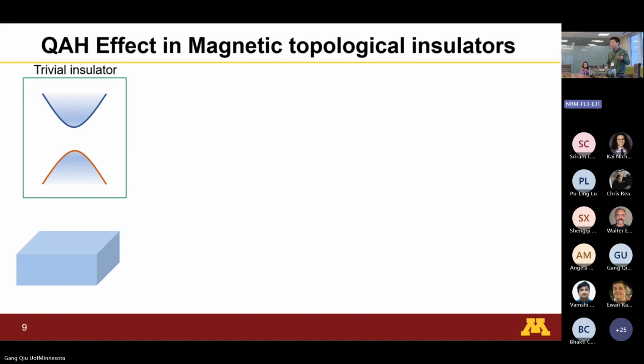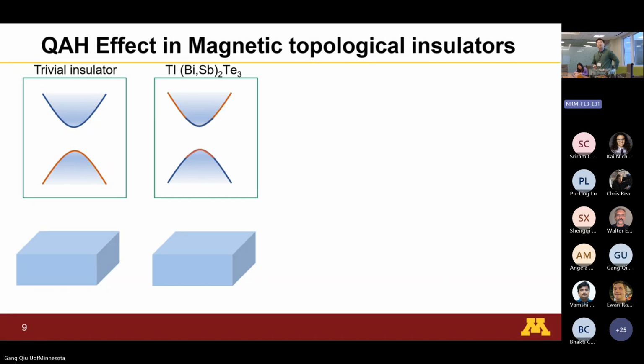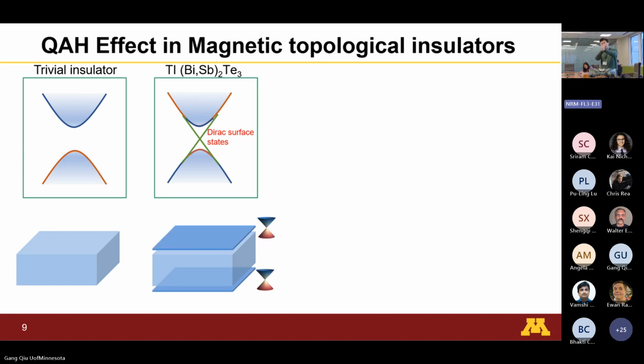So we know insulators, right? You just have a conduction band, a valence band, and a gap. Now you have probably heard about topological insulators by now. It's still an insulator, but the conduction band and valence band are flipped. Inside these materials, the conduction band orbital is actually lower than the valence band. So if it goes out of the system to the vacuum, it has to come back. In this case, at the surface of this material, you will have these Dirac surface states. In other words, these surfaces are actually metallic. The bulk is insulating, the surface is metallic.